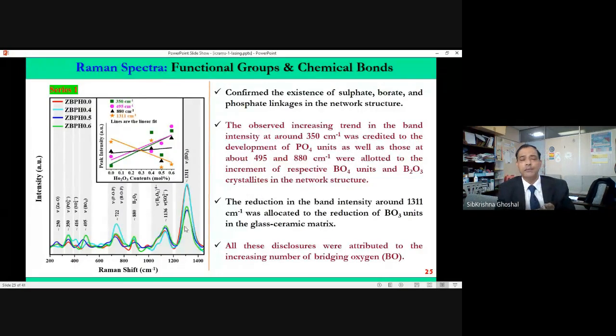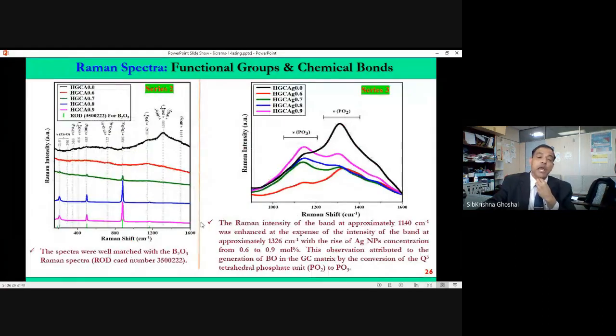Then we go to the Raman measurement. In the Raman, we also see the same peak, and we confirm that these crystallites have formed. Then we analyze the Raman peak more and more to see where is the phosphate, where is the borate, because borate and phosphate are very interesting materials. They can form different kinds of units, PO2, PO3, PO4. Similarly, borate, BO2, BO3, BO4. But remember, BO4 and PO4, that means phosphate in 4 and boron in 4, are the most stable units.